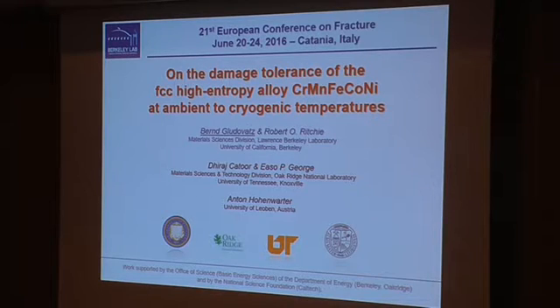When we look at the sample that was tested at liquid nitrogen temperature, we can see a similar picture to some extent. We also get a lot of such deformation cells within every individual grain. We get pronounced cell structures, a lot of dislocation activity, but also in addition to that, we get a lot of such nanoscale deformation basically in every individual grain, which becomes even more obvious when we overlay this EBSD scan